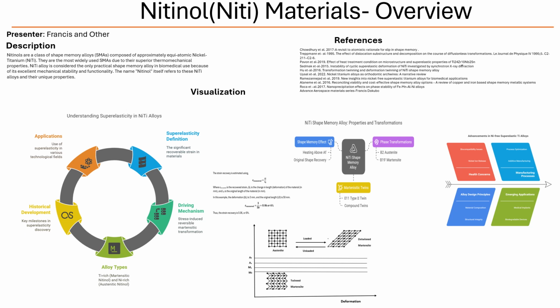And this has led to research into alternative materials, right? What's the latest on those nickel-free superelastic alloys for biomedical use? Absolutely. The whole nickel allergy issue has really driven researchers to search for alternatives. And titanium niobium, or TiNb alloys, have emerged as a really promising candidate. They can exhibit superelasticity, but generally their recoverable strain is not quite as high as NiTi. And this is often because the changes in their crystal structure during transformation are smaller and they're more susceptible to slip at lower stresses. But the interesting thing is that by adding a third element, like zirconium, you can significantly increase that recoverable strain in these TiNb based alloys. So it's about finding the right mix of elements to get those superelastic properties without any nickel involved.